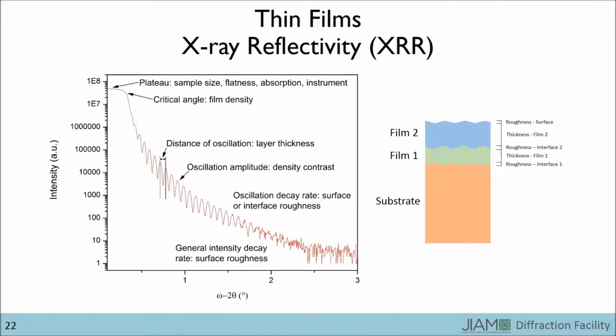Another technique that is beneficial for thin films is X-ray reflectivity, or XRR for short. XRR utilizes the Bragg-Brentano geometry where the source and detector both rotate, but the angles are kept smaller than for standard powder diffraction. In the example here, omega did not get above 3 degrees, which means that 2 theta did not get above 6 degrees.